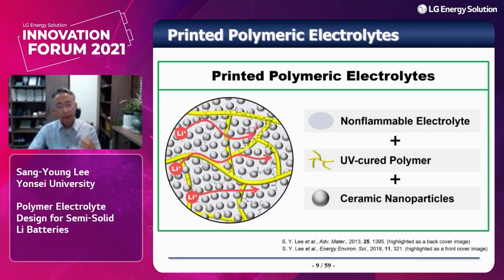To enable structural integrity, we have employed a UV-cured polymer network, represented by the yellow line. In addition, we have incorporated ceramic nanoparticles to control rheological properties and to ensure the structural integrity. Here, as you can see, the lithium ions are allowed to move through the non-flammable electrolytes like this.